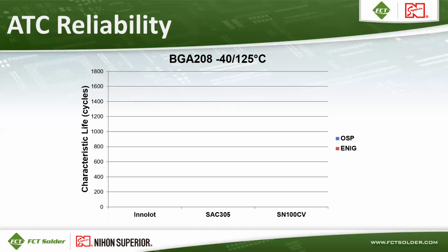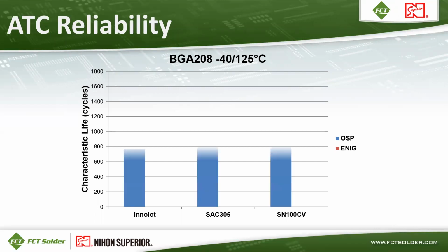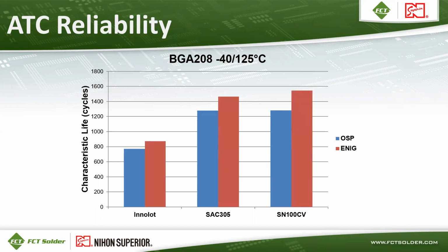Here's the same data for the BGA 208 component. Innolot had the shortest characteristic life in this case. SAC 305 was a little higher, and that matched SN100CV on OSP. And then on ENIG, that same trend was generally followed, although SN100CV is slightly longer life than SAC 305.